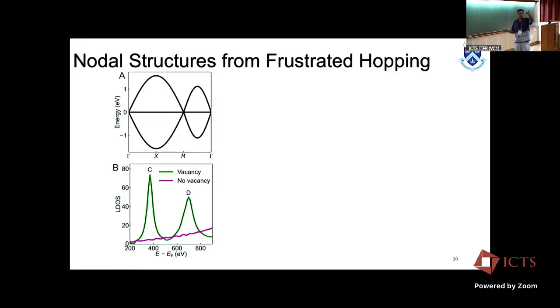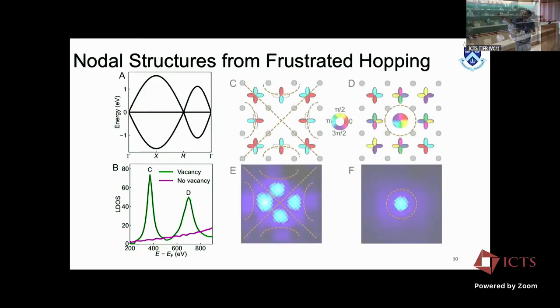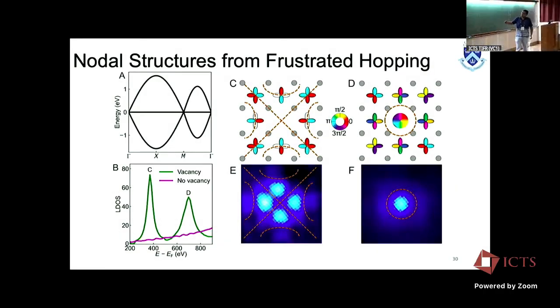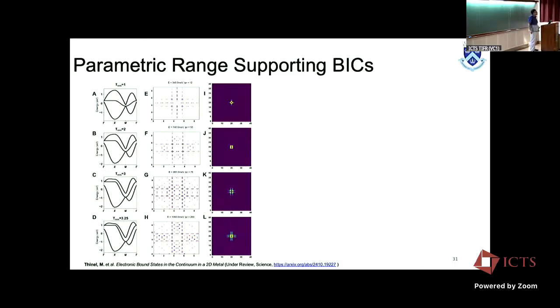And now, in answer to your question, Kedar, what we did is we played with this in tight binding. So in tight binding, you can make a model of this. You can put a defect on a particular site, and then you can vary various things, like nearest neighbor hoppings. So once again, this is the phase structure of these 2 bound states. There's one which has nodes. That's the one that I showed you earlier. And there is another one that you can construct, which is enhanced at the center and has a radial node, exactly like what we see in the experiment. So that's precisely what we see. And so there's only 2.